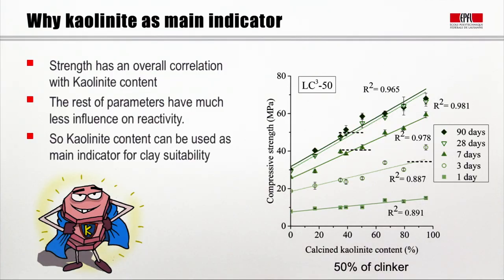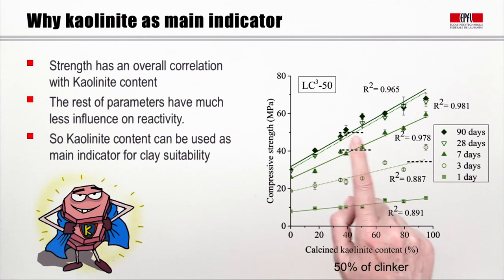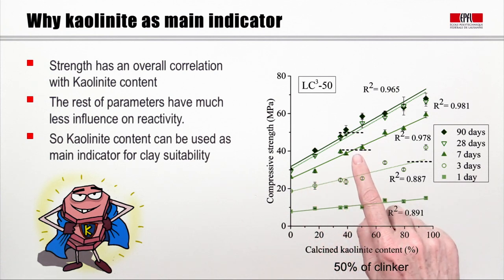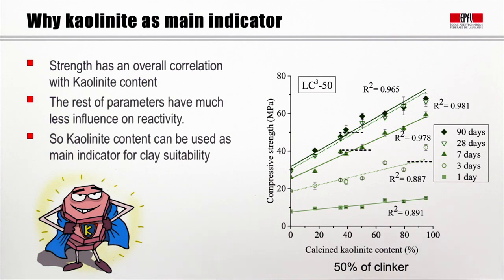On this graph we see the very important results of the relationship between the kaolinite content of the clay and the strength developed in a mortar. There is a linear correlation between these two. The dotted lines show the reference strength of pure OPC cement. At seven days, if we have a kaolinite content above about 40%, we'll have a similar strength to the Portland cement reference, which is why we say above 40% is really what you need.